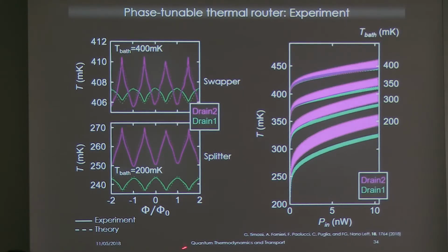What is interesting is that here are just two traces of drain 1 and drain 2 at different bath temperatures, 400 and 200 millikelvin, and roughly 60 picowatt of injection. In this range we see that there is a full separation and just splitting. The dashed lines refer to the transfer Hamiltonian model of the thermal balance equation, which fits what is represented. There is a nice accord, as you see. And by increasing the temperature again, we go into a regime of swapping, which can also be fully taken into account with the same equation.